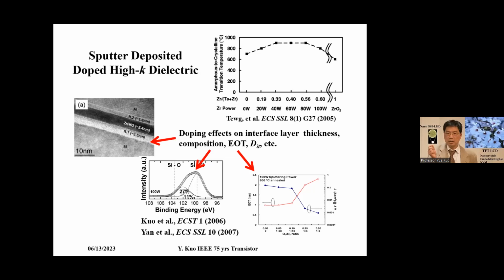So we reported in the late 1990s that we use a doping method, adding an element into the metal oxide, and you can see an increase of the crystallization point by a few hundred degrees. So this keeps the gate dielectric in the amorphous state up to, for example, 900 or even above. With the doping process, we can even deposit high K with sputtering. Because of doping, we change the interface characteristics.